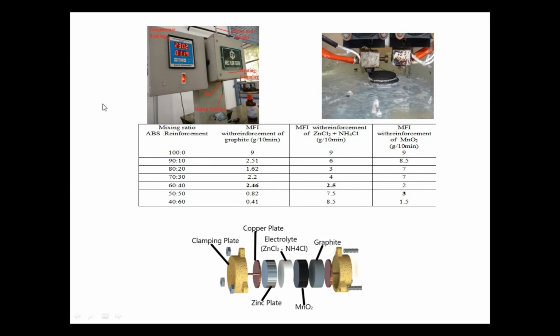A similar study was done with higher proportions, let us say 20%, 30%, 40%, 50% of graphite, and you can see that there is a trend. First it was decreasing, then increasing, and then decreasing again with the different ratios of the graphite reinforcement. Now, a separate study is required. Why? With the reinforcement of graphite, earlier there was a decrease in the MFI, then an increase, and then further a decrease. This is really important to understand, and for this purpose we go for thermal analysis and FTIR analysis to know what sort of bonding mechanism is responsible for this type of behavior.